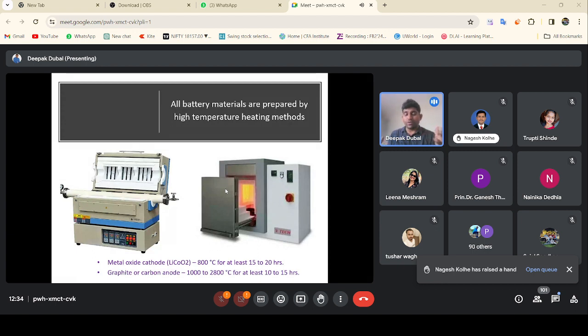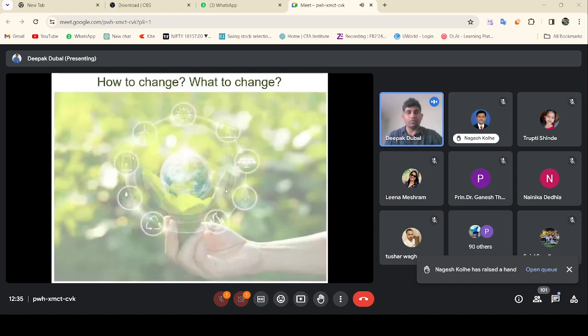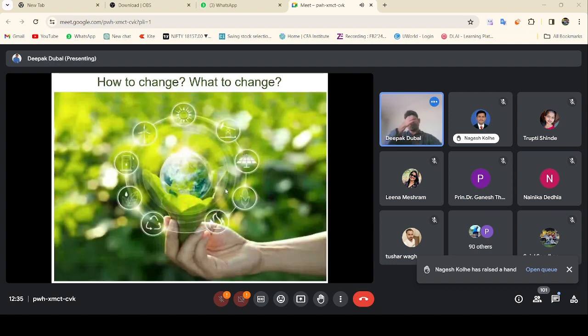If I want to synthesize any carbon material, we have to go from 1000 degrees to 2800 degrees, because graphite can be graphitized at 2800 degrees Celsius, and the reaction time is super long. So unknowingly we are using all these sources to manufacture the materials, and it is contributing a huge amount of emissions. So what we did is, we need to find new processes, and those processes need to be cleaner first, and second, they need to be efficient and fast.